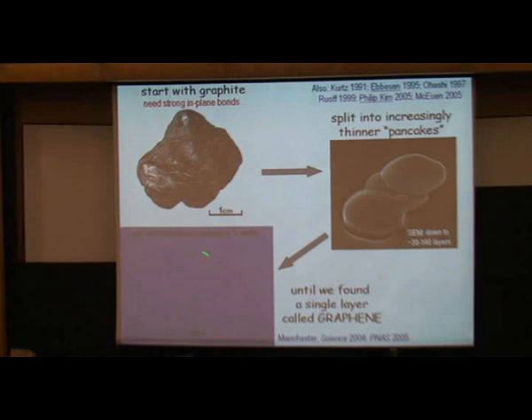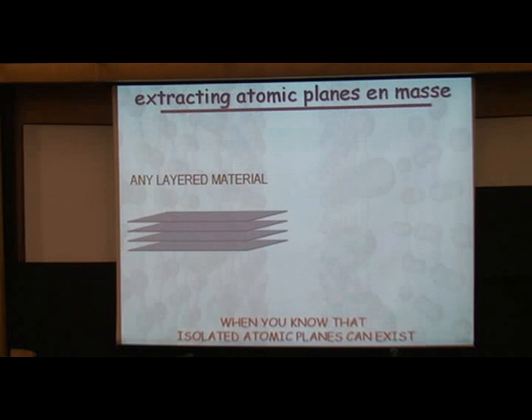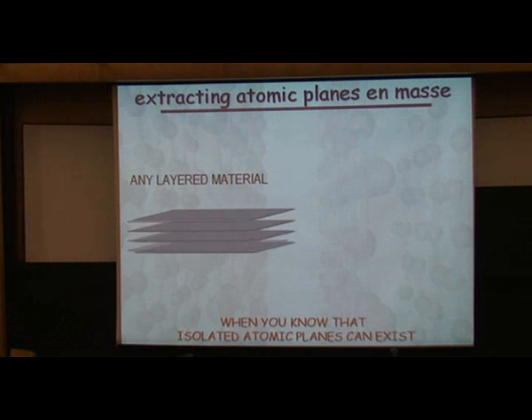You probably see here a subtle contrast, because the light is a little bit too bright, but there is a single layer that you can see, a single layer 1 millimeter across. In this case it's deposited on a silicon wafer. You can deposit those individually extracted layers on anything that you want. The step from here to here was not trivial, but this is history. The final result is that we have this sort of layer. Surprisingly, when you really know something that is worth studying, then you can do plenty of tricks.